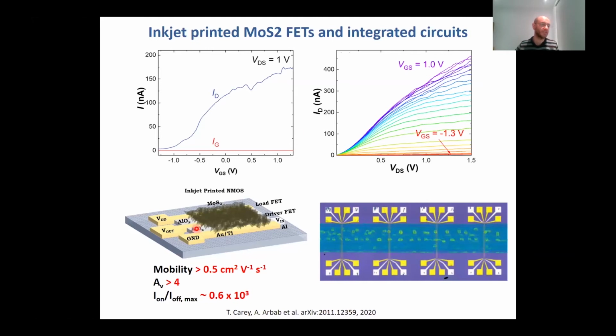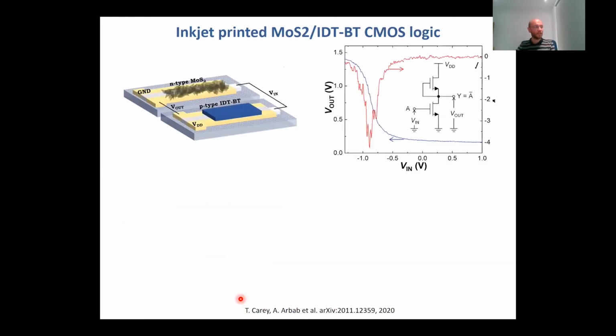many FETs in sequence. So for example, here you are seeing two FETs working together, showing a mobility of around 0.5 centimeters square per volt per second, which is actually underestimated a little bit because of the contact resistance that is pretty high in these devices. So we believe that this could be around a few centimeters square per volt per second. But the important point here is the on-off ratio. This is much higher than graphene, and is actually moving towards what you really need for printed devices and printed